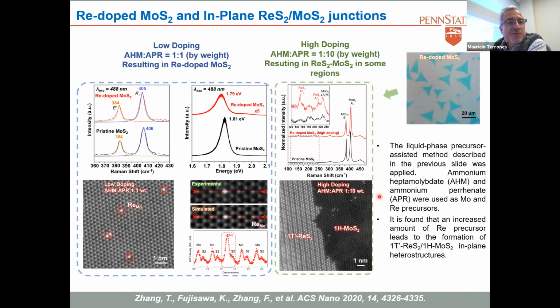We can also do it with rhenium. So we can dope with rhenium, again rhenium disulfide, rhenium-doped molybdenum disulfide. And sometimes when we do the right things, we have this in-plane hetero interface of 1T prime rhenium sulfide with the 1H hexagonal semiconducting moly sulfide with the rhenium sulfide. So this is nice. And here we can see the dopant, right? Shining more than the other ones by the Z contrast. So we can, in principle, just dope with any element if you do the right chemistry.